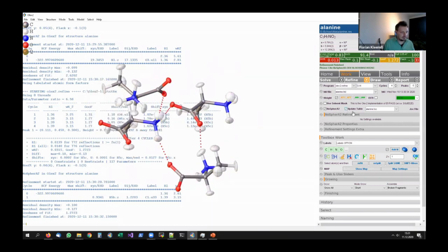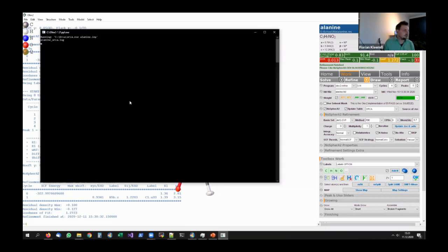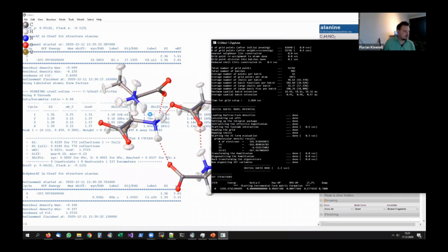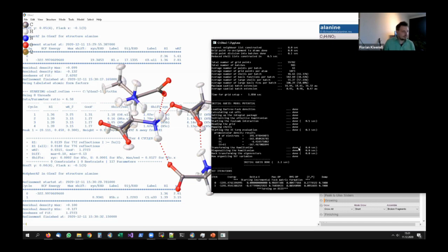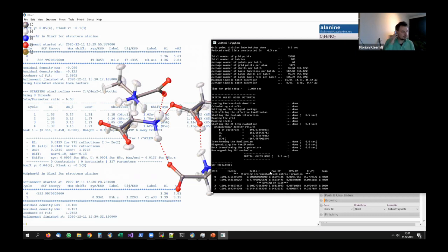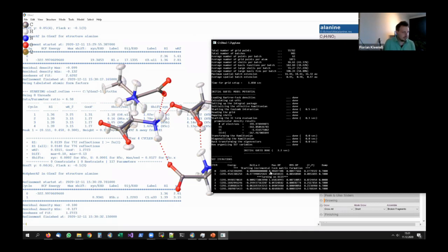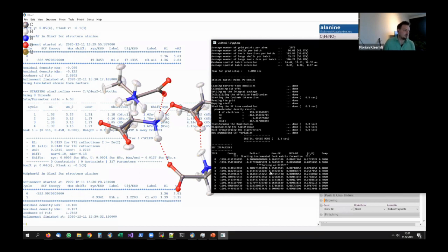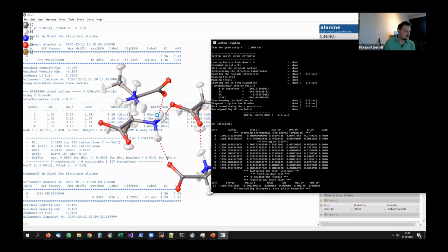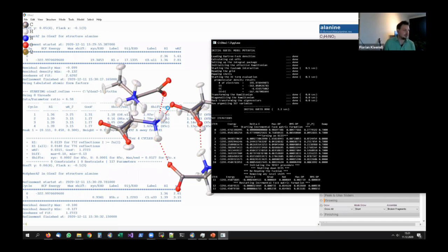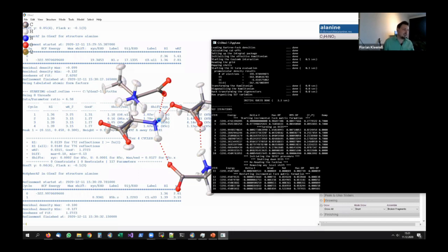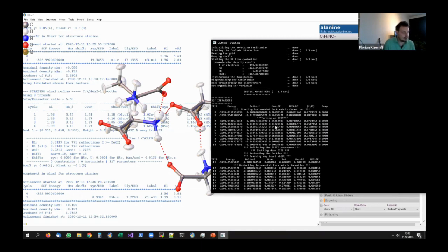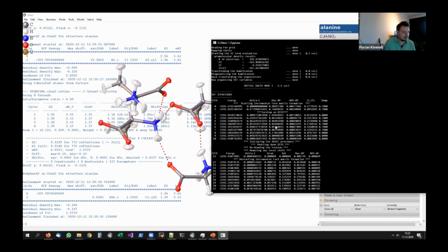So if I now click Update Table, the calculation will have much more atoms, 52 atoms. It starts counting at zero. 52 atoms is much more than one alanine molecule, so this calculation takes longer. But ultimately, it will describe the hydrogen bond that this nitrogen-bound hydrogen forms with the neighboring molecule in a much better way, and this will also improve the ADPs of our nitrogen atom. So hopefully this will start converging soon, and then we can see the result.